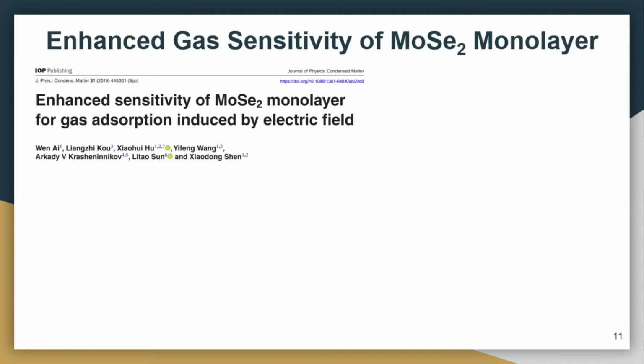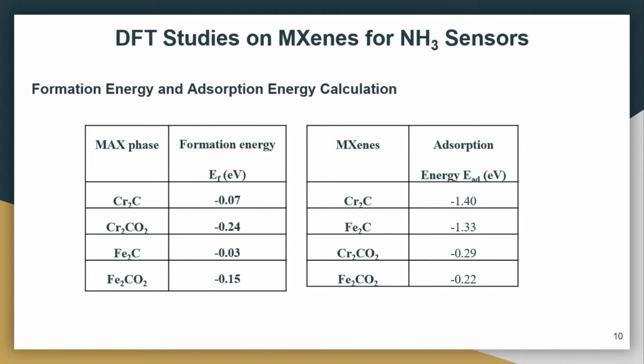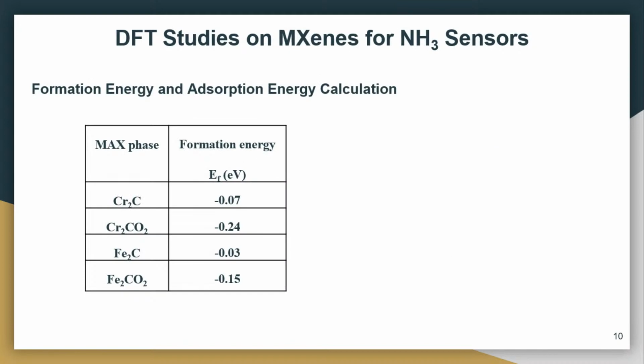This is a table. Yeah. So we calculated the formation energy. Here, for Cr2C, the formation energy is around minus 0.07. Then we can say that there is a possibility of formation of Cr2C. Even Fe2C also, it's minus 0.03. So what we can identify from this is that the possibility of pristine Cr2C is higher compared to your Fe2C. But when it's functionalized with oxygen, the formation is much higher than the pristine material.